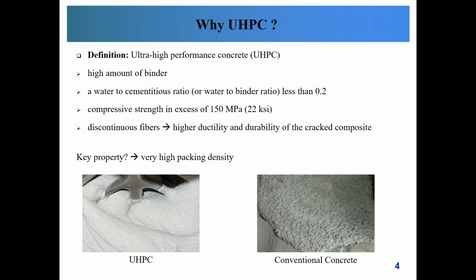Why UHPC? Most of you have probably already heard of UHPC. It is a cementitious composite with a relatively high amount of binder in comparison to conventional concrete. It is designed to use a water-to-binder ratio of less than 0.2 and achieves compressive strength in excess of 150 megapascal or 22 ksi, and the addition of tailored discontinuous fiber reinforcement leads to significantly higher ductility and durability of the cracked composite. The key for the strength and durability properties is a very high packing density of the matrix.